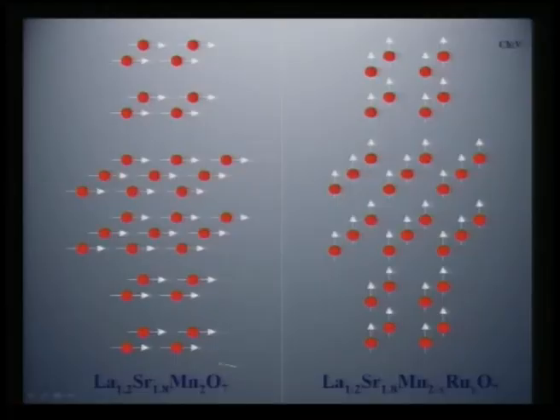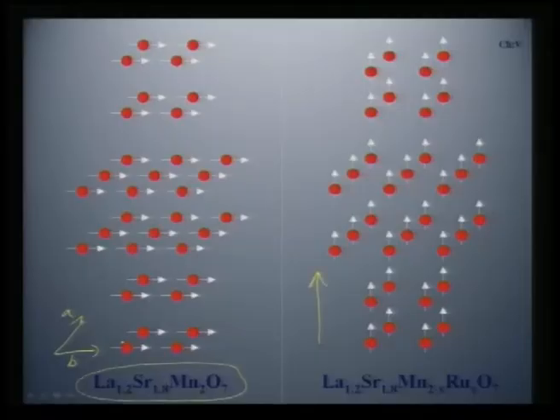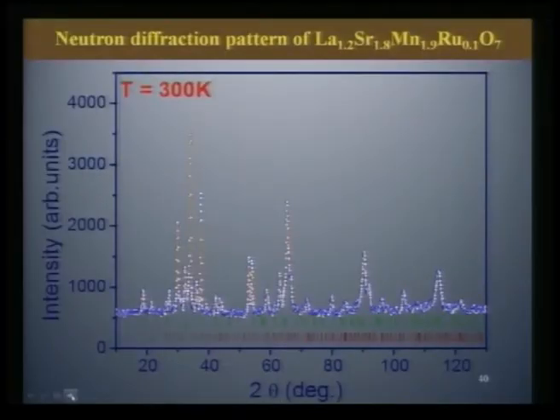You can see here the spin orientation of the manganese core spins is confined in the AB plane, whereas when you substitute ruthenium, the neutron diffraction studies clearly tell us that there is a rotation of the spins along the C direction. It is no more confined in the AB plane, it is now coupled in the C axis. Now, when it is coupled in the C axis, this can promote or enhance your ferromagnetic ordering and your metal insulator transition. It is not a guess, we can see that from the neutron diffraction case.